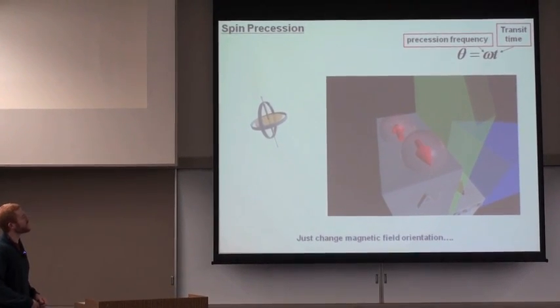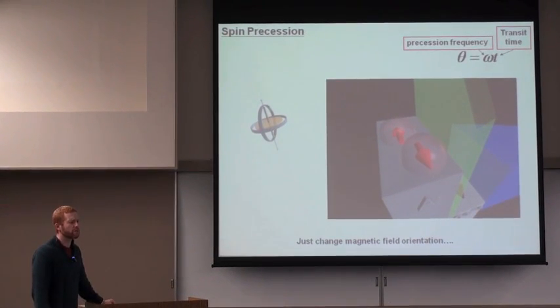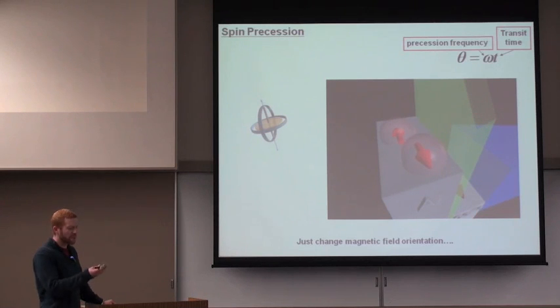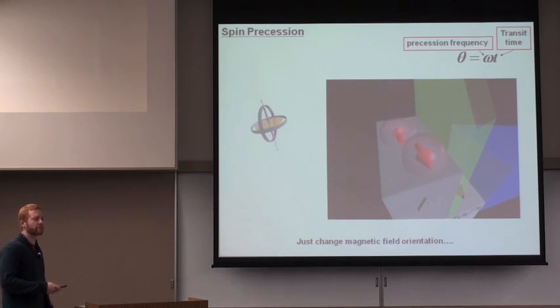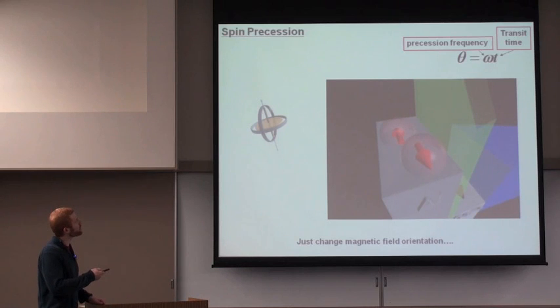Now, what happens, of course, is that each one of these electrons is being injected into the silicon with a definite spin orientation that's determined by the magnetization direction of the injector. And so the spin orientation accumulates a precession angle determined by the strength of the perpendicular magnetic field, which determines the precession frequency, and the transit time, the amount of time it takes for the electron to get from the injector to the detector. And that, of course, is inversely proportional to the internal electric field. So we can determine this precession angle, theta, with magnetic field or with electric field.